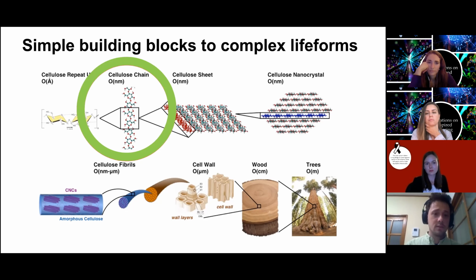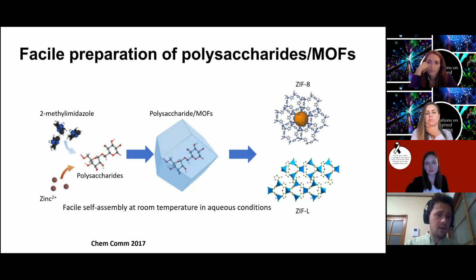So starting with cellulose, we found that cellulose and other polysaccharides can act as a sink to concentrate metal organic frameworks. These metal organic frameworks we use were just 2-methylimidazole and zinc. Super easy. You mix them in water at essentially aqueous conditions, and rapidly you start forming crystals. Interestingly, the crystals can have two different isoforms. I won't have too much jargon in there, but that's ZIF-8 and ZIF-L. It's the same constituent building blocks, but they take on different crystal shapes.